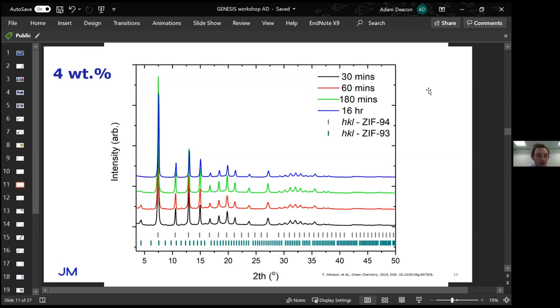If we increase the concentration of this reaction further, we see this impurity appearing at low reaction times but retained further on in the reaction up to three hours, and we have to leave it to 16 hours for it to produce a phase pure material. This isn't too problematic for us—16 hours versus three hours is really not too much of an issue. We wanted to see if we could increase this concentration even more by leaving it longer.